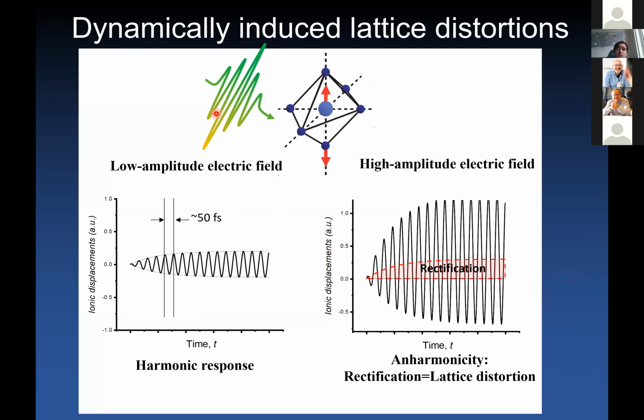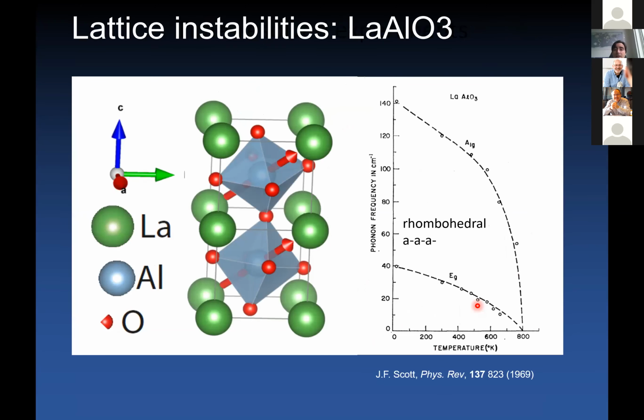So we want to dynamically induce lattice distortions. And if the amplitude of your electric field is low, then you will only reach a harmonic response regime. So you will induce some oscillations around the equilibrium positions of atoms that will rapidly decay. And this will not have profound consequences on the electronic properties of your material. Instead, if your electric field has a significant amplitude to touch upon the anharmonicity of your crystal lattice, then you can have the phenomenon of rectification of your phonon field, and then you can generate lattice distortions. So the key here is to displace ions with large enough amplitude to be able to experience an anharmonic response of the lattice.